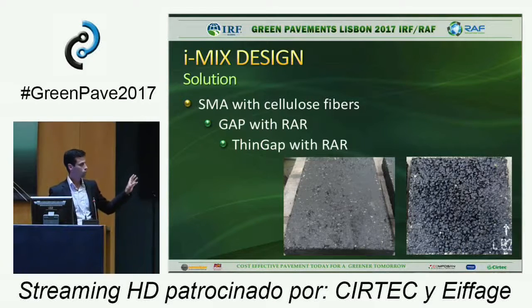But this one was when I started the PhD. I was trying to make the mix design of the SMA mixtures, and I didn't quite know well how they work. During that time, I always read in the international literature that you have to use at least 6% of bitumen. I was trying to put in 6% of bitumen, and I used the limits from the United States, from Germany, and stuff like that. We tried to change the curve that we were using, but we didn't manage to put in more than 5.5% of bitumen. And when we started to use the mix design in the very early beginning of it, we were able to put 1% more bitumen and have that kind of macro texture.